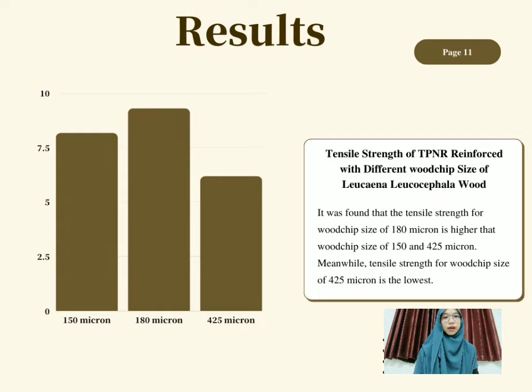The tensile strength of TPNR reinforced with different woodchip sizes of Leucaena leucocephala woodchips. It was found that the tensile strength of woodchip size of 180 micrometer is higher than woodchip size of 150 and also 425 micrometer. Meanwhile, the tensile strength for woodchip size of 425 micrometer is the lowest.